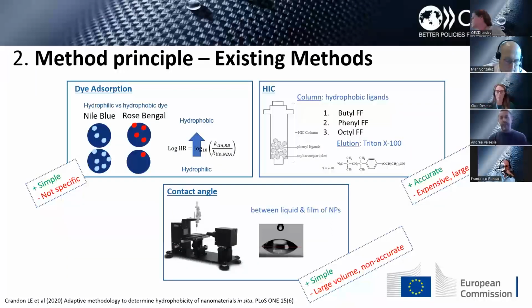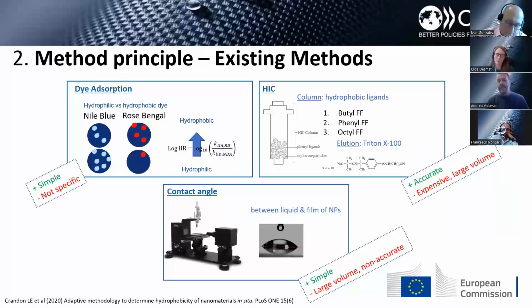If you want to use it for nanomaterials, you can, but the problem is that you need to create a homogeneous film of your nanomaterial in dry conditions. So you need a large volume of nanomaterial again, and it is not really accurate, because the measurement of hydrophobicity comes from a mathematical model which requires that your material is flat. When you use a film made of nanoparticles, this is not flat by definition. So this method is not really accurate.